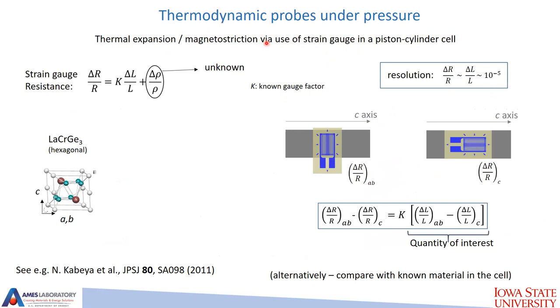So another one is thermal expansion under pressure using strain gauges. Again, I assume everybody knows it. A change of resistance of a strain gauge is the change of length of this net of wires plus the change of resistivity, which is unknown. To get rid of this term, either you glue two strain gauges in two different orientations and look at the relative change, delta L over L along AB minus delta L over L along C, or you put another known material in the cell and do measurements relative to this known material.